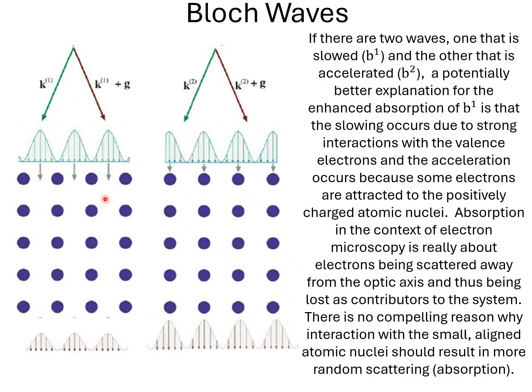because in the context of an electron microscope, if you have a big thick piece of material and you shine electrons through it, and the image is just basically dark, it's not because the electrons are all sopped up by the material. It's because the electrons are scattered out away from the optic axis. They're scattered into the sides of the microscope. So absorption in that context is really more scattering.